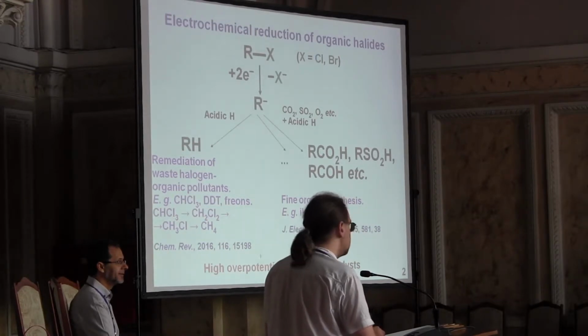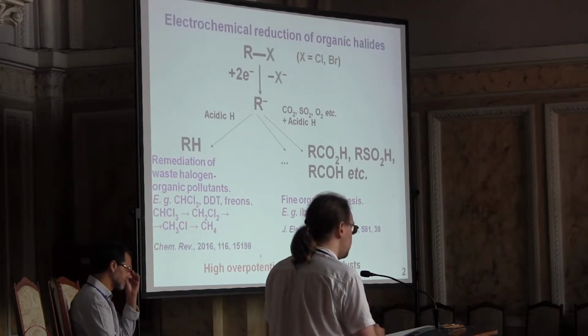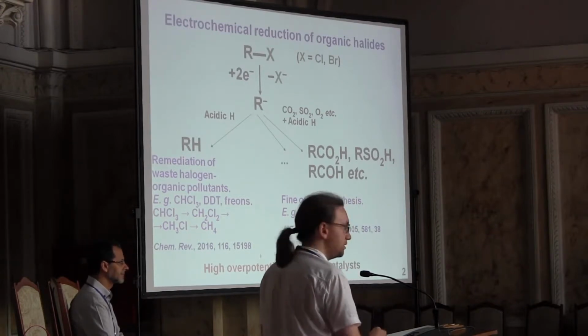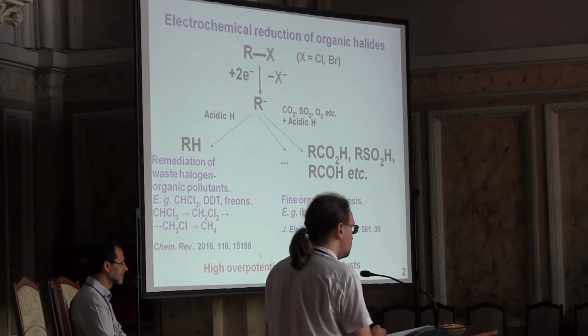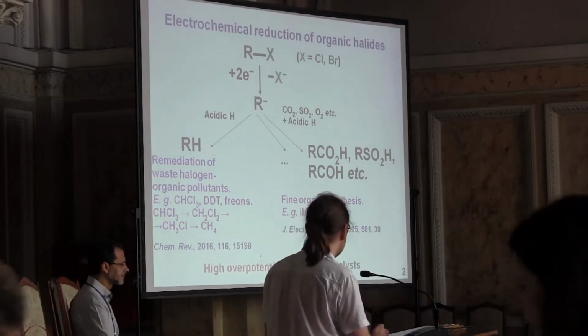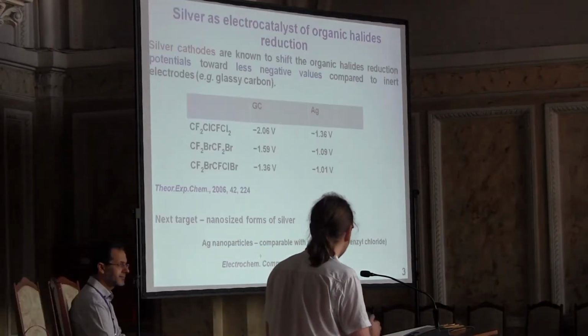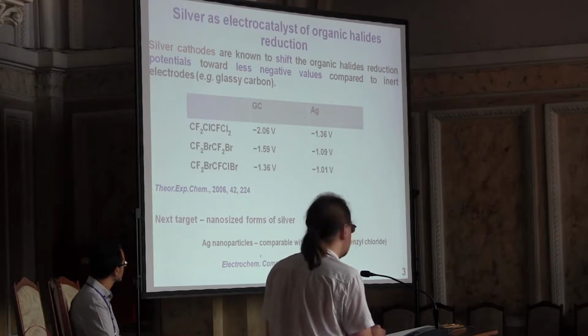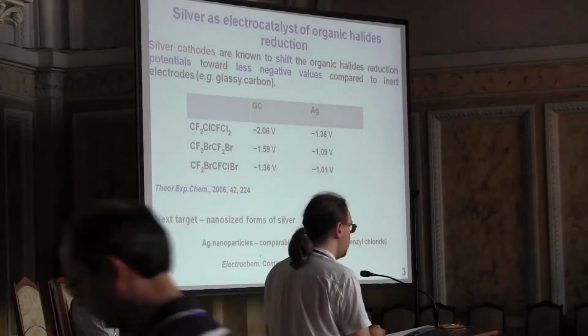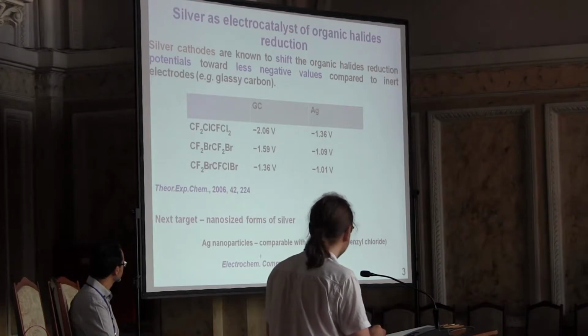However, such processes undergo with high overpotentials, which is not desirable for practical use. But such overpotentials can be lowered by use of appropriate electrocatalysts. Silver cathodic materials were shown to be efficient electrocatalysts for such processes, which manifested in a significant anodic shift of potentials of such processes on silver cathode compared to inert cathode, such as glassy carbon or so.